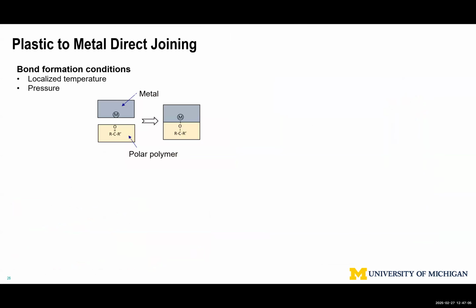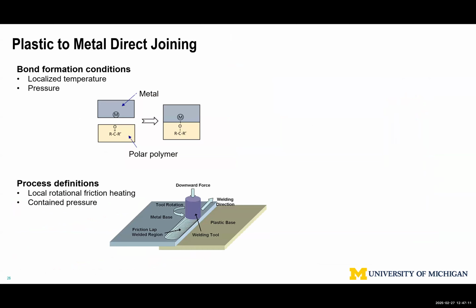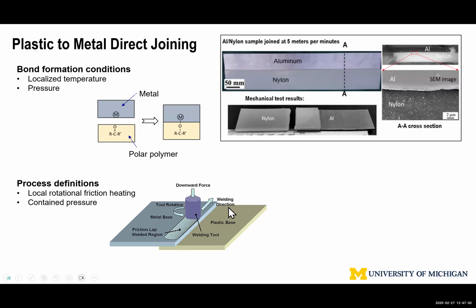And then another one is dealing with plastic to metal direct joining. We can do it by introducing localized pressure and temperature. That's the key. Even this morning I had a meeting with the LSA polymer chemistry professor. They were puzzled how this process would work. They're going to develop an experiment to observe. Under that pressure and temperature condition, we can produce molecular level bonding, and that bond is so strong at the interface, with no micro mechanical interlocking. That means the superb strength has to be accounted for by the presence of molecular level bonding.